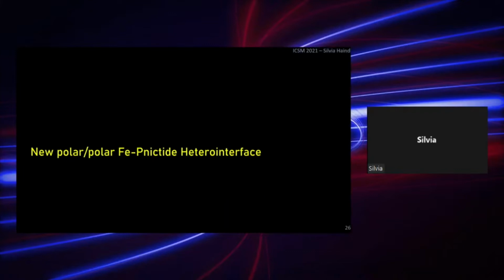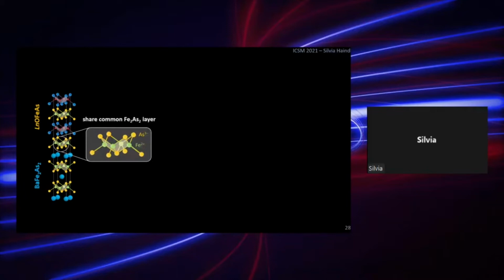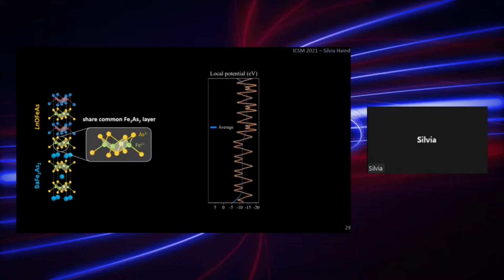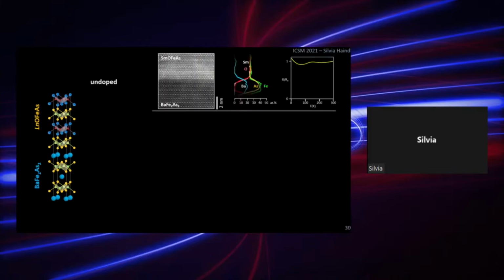So let us now go to the new polar iron pnictide hetero interface, and we now join the iron oxypnictide on top of the barium 122 layer. They have this commonly shared iron 2 arsenic 2 layer. And when we calculate the local potential and the average, we see basically a smooth variation of the average local potential. So this should be a stable and clean interface, and this is what we indeed have observed.